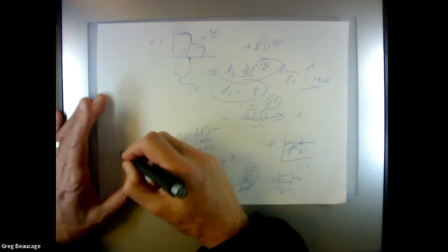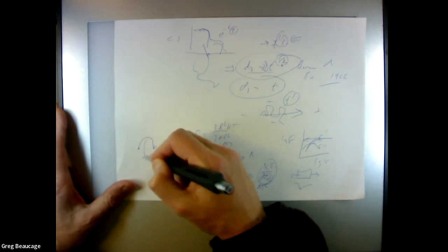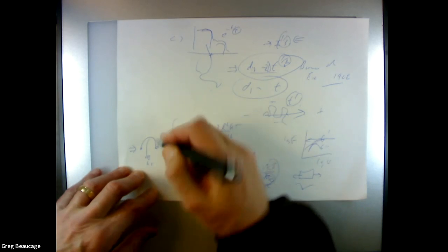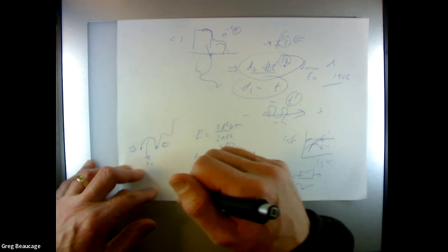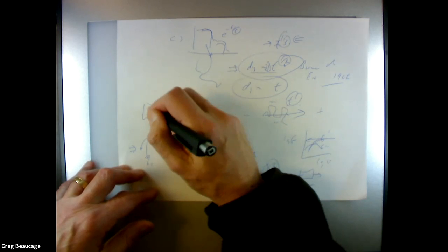The modulus goes with temperature because the chain is like a jump rope, and temperature is like swinging the jump rope, and the modulus is like the force that pulls in on the ends of the jump rope as you swing it. If you swing it harder, it pulls in more. So the whole rubber is like a bunch of jump ropes pulling in, so you get a higher modulus at higher temperature. It's entropically driven. It's the same source as the pressure of an ideal gas: pressure increases with temperature.